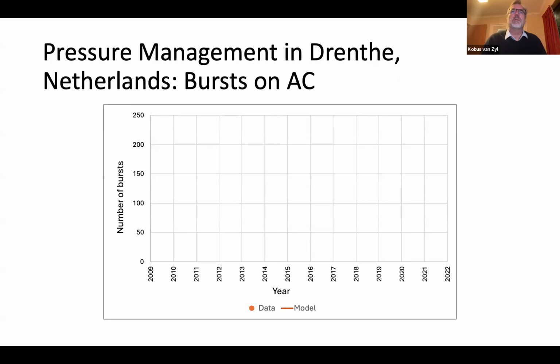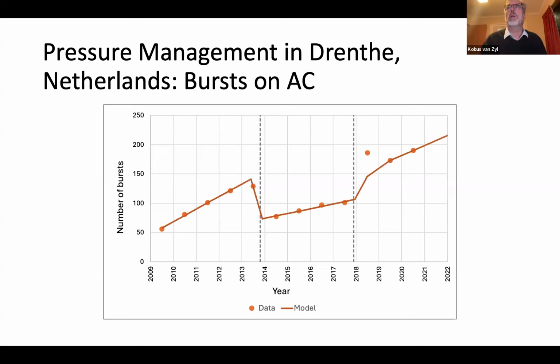And this data shows the failure rate of the AC pipes in their system. And so what you see is that where the pressure management was implemented, before that you see a rise in the failure rate. Then after pressure management, you see a sudden drop. It continues to rise, and then here it jumps up and is higher, not as high as this line would indicate, but significantly higher than in this period. And so we fitted our model to this, and we could see the model can reproduce that behavior quite nicely.